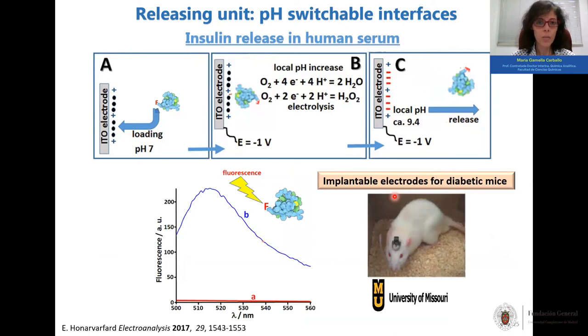Taking advantage of this, we performed insulin release in human serum based on the same concept. We first loaded insulin, since it is negatively charged at pH 7. And after loading it, we were able to release it by increasing the pH by just applying potential. In collaboration with the University of Missouri, we were able to implant these electrodes in diabetic mice.